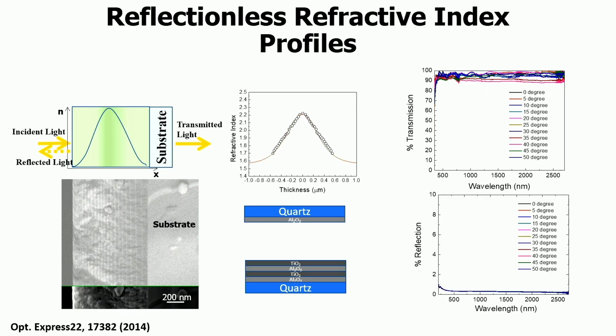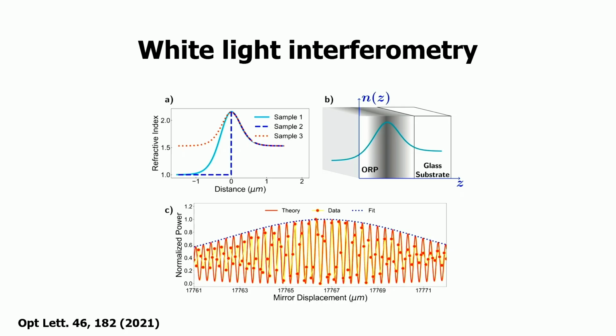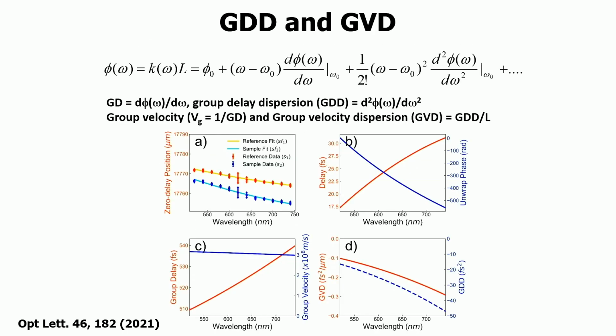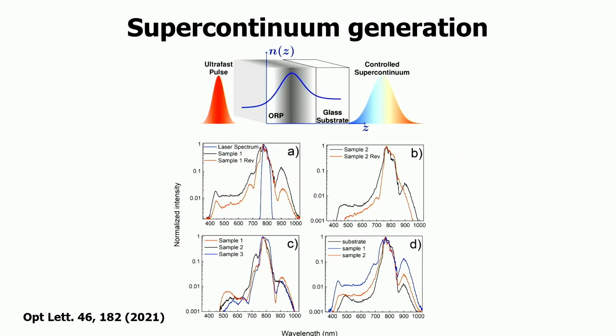One interesting property of these structures is there is a theoretical prediction that these can have broadband negative GVD, group velocity dispersion. So to study that, we did white light interference measurements on 3 different structures. For example, there is a full reflectionless potential, there is a half potential structure, and then a reference sample, which is just an uncoated substrate.